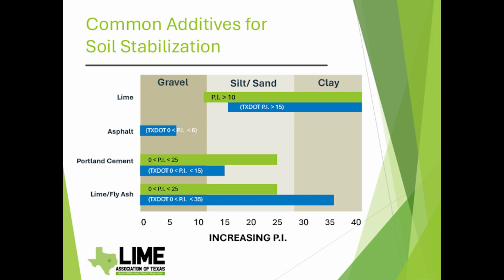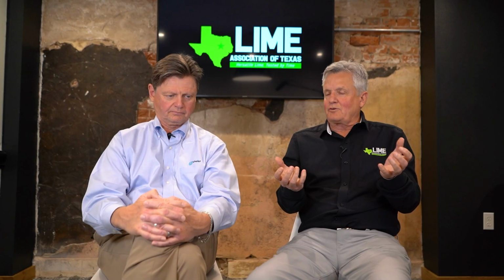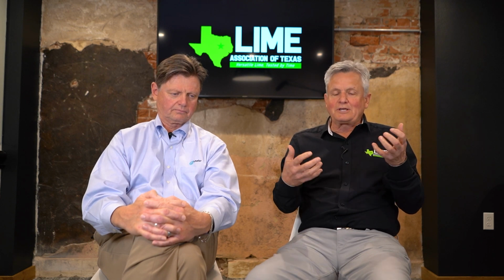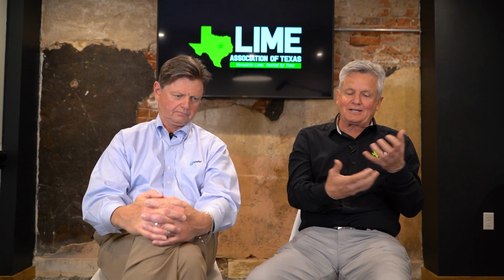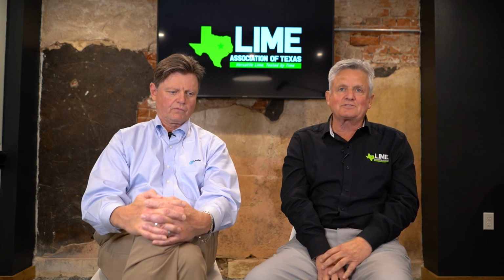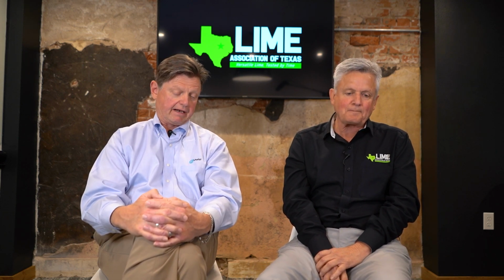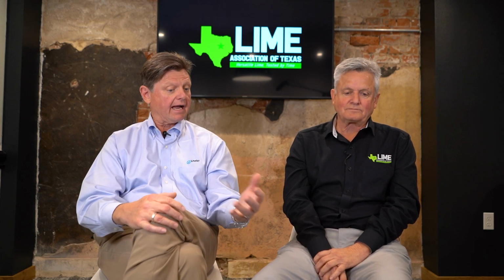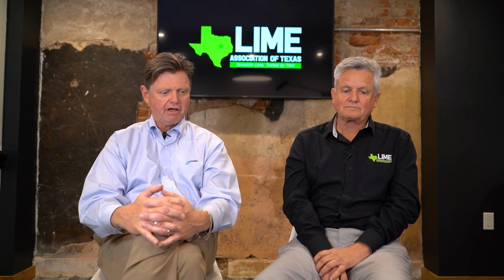You can use asphalt. You can use Portland cement. It works excellent in those kinds of coarse grain materials. Or you can use lime fly ash combinations. But the only way that lime will work is if you get something that has alumina and silica in it, so you have to get the fly ash, which brings that in to form pozzolan. A lot of times the lime will be a catalyst for the fly ash, and you get that kind of reaction.